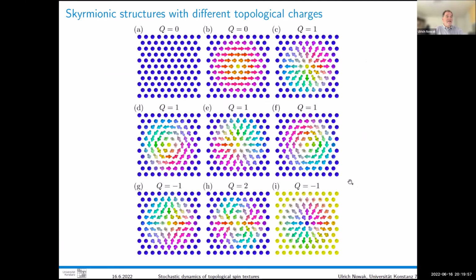Here's some example for spin structures. So the ground state, all blue, if you calculate this integral, has topological charge 0. And all structures that you can reach by a continuous transformation, like this one here, where you rotate the central spin to the right, then you will get something like this. That has also a topological charge 0. But the skyrmion has topological charge 1.